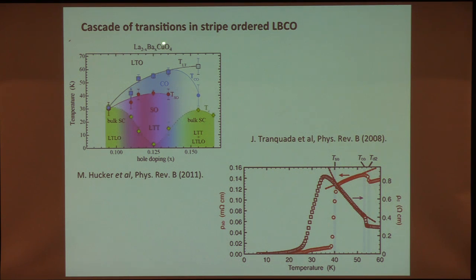But now I want you to see something, which is as I come down as a function of temperature here, although what's marked here is a very low superconducting transition temperature because that's the temperature at which the Meissner effect is first determined, if you measure the resistance in the more conducting in-plane direction as a function of temperature, you see that it has an order of magnitude drop. So it's some substantial form of two-dimensional superconductivity that onsets. Notice this is called TSO, that's the onset of spin density wave order. So again, we have this coincidence of two completely unrelated broken symmetries.